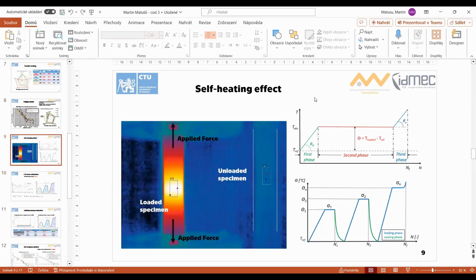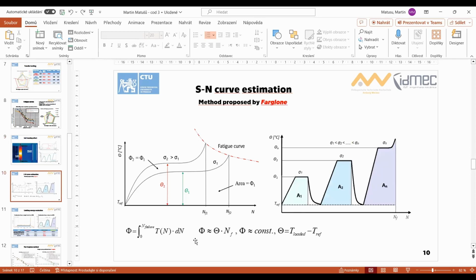Because if you look at this graph, we can see that the second phase is generally the longest, because the first phase, in this testing condition, around 100 Hertz with this material, is somewhere around 5,000 to 7,000 cycles. And the second phase depends on the amplitude obviously, but it can be 99% of the temperature evolution, and the higher the amplitude goes, the shorter the second phase gets. But with this assumption that you take only the stabilized temperature and do something like a rectangle, you can establish the number of cycles to failure.